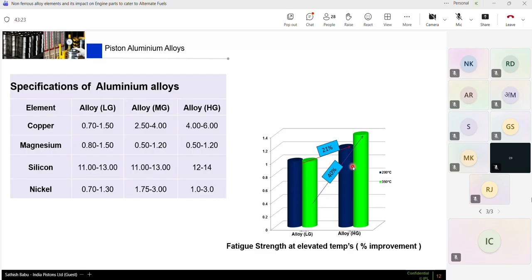So having all this thermal loading conditions and other things, the requirement of increased percentage of copper content and nickel content plays a major role in improving the fatigue strength of the material at higher temperatures. Typically, these kind of higher temperatures of more than 350 degrees are seen on the piston side, because it can be more than 350 degrees on a diesel piston.